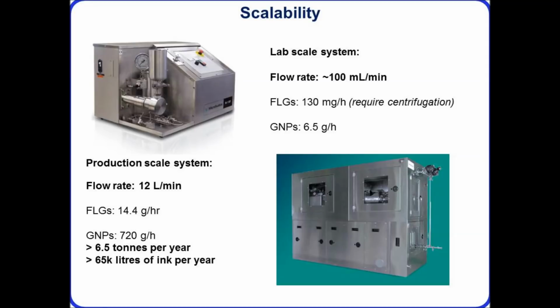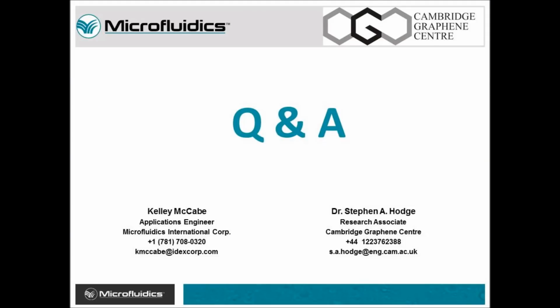Okay. Thank you. Another question that we received was, what are the maximum temperatures a solid-liquid mix may reach inside the microfluidizer processing chamber after an hour of continuous processing using the highest pressure and the smallest chamber? So this is the reason we have to use the cooling system after the outlet reservoir, because if we process without any cooling, then the chamber can reach temperatures of around 60 degrees, and that's after maybe a few minutes of processing.